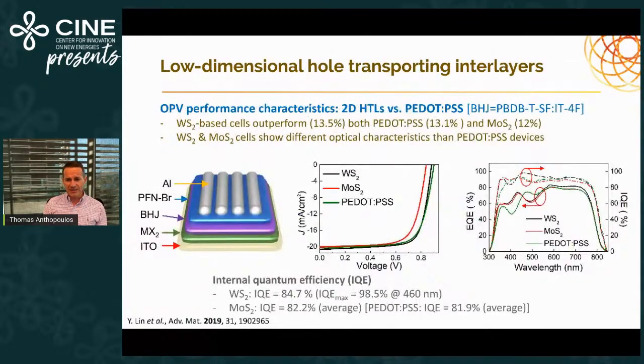And what we then did, we created devices, and we were very surprised to see that despite the atomic layer thicknesses of these two-dimensional materials and the way we have deposited them on top of ITO by just simple spin coating, we're able to push the device efficiency to over 17%, which at the time was the maximum for these specific combinations, especially with NFA materials such as Y6 combined with the right donors. The origin of this performance enhancement comes both from the VOC, but also the higher current.